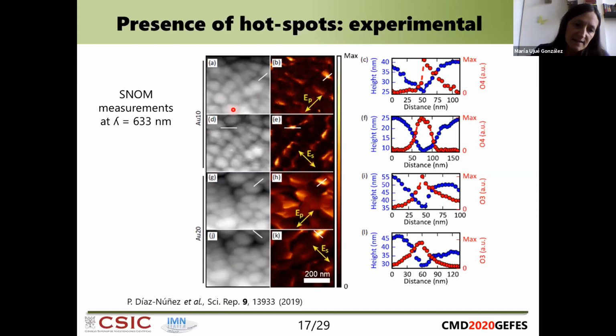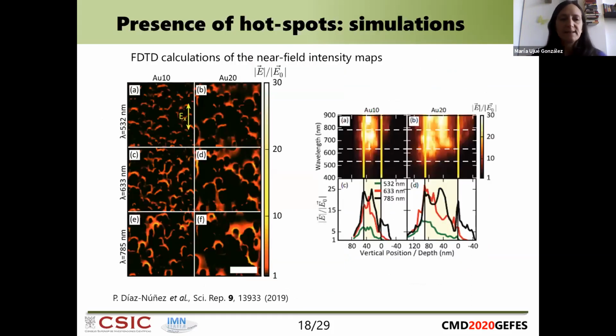So here you can see the morphologies of the short nanocolumns, the 50 nanometers, and the 100 nanometer long length. Here you can see that sometimes in between gaps of nanocolumns, we have spots of high intensity of the field, which means that we have these areas where we have this concentrated electromagnetic field that could be interesting then to provide a surface Raman enhancement. And the measurements could be performed only at 633 nanometers wavelength.